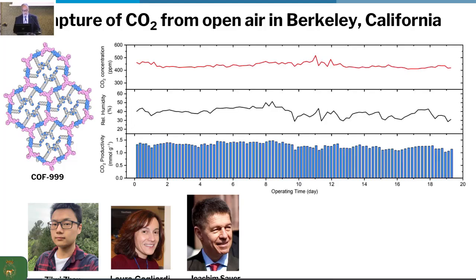So here's the experiment that is truly a fantastic development. We took open air in Berkeley and measured the CO2 concentration in the air outdoors. Then we took a measurement of the relative humidity in the air. And this is over a 21-day period. And then we looked at how much the CO2 was taken up by the material. So basically you take a powder of the material and then you expose it to air. And the air is coming from outside. And you pass it through the material and you look at what's happening on the other side of the material.